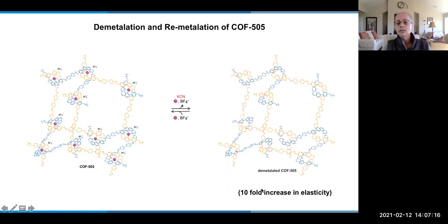And we measured the elasticity of this material, and it turns out that it's tenfold more elastic than this metallated COF. This really propels the woven structures into this idea of dynamics, and then how to incorporate these into composites to make very tough materials, where these woven units can absorb energy and therefore make for tougher materials.